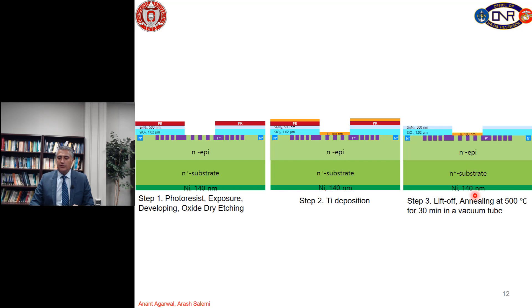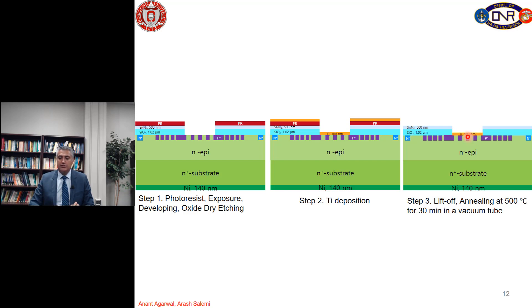After liftoff, we anneal the sample at 500°C — not higher — because we need a Schottky contact here. If we increase the temperature to 900 or 950°C, we would form an ohmic contact on the P+ region. For JBS diodes we need a Schottky contact; ohmic contact is needed for MPS diodes. So 500°C for 30 minutes in a vacuum tube is sufficient for a good Schottky contact.